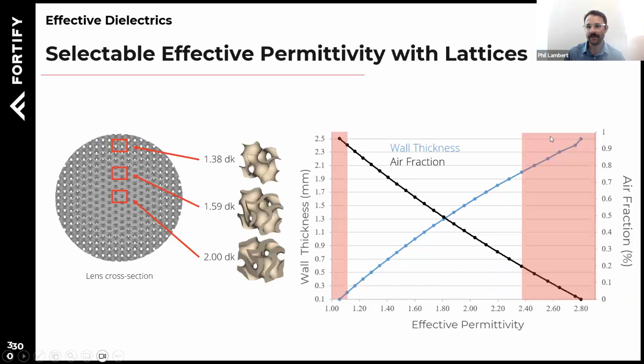So let's look at a chart here. I think it'll tell that story a little bit more clearly. So here we have the cross section of a lens, and we have our gyroid unit cell here. The walls are very thin, the pores are quite big, and we are realizing a very low effective dielectric constant. But as we go to thicker walls and smaller pores, we get to a higher dielectric constant. Now, if you bring that concept onto a chart, where on the x-axis we have effective permittivity, and on the y-axis we have wall thickness and air fraction.